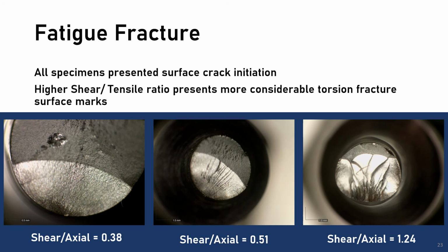With access to the fatigue fracture surface, we can now compare the fatigue fractures between different shear and axial ratios. We can see that lower shear in relation to the axial presents a fracture surface very similar to tension-compression fatigue tested specimens, whereas as we increase the shear in relation to the axial, we start to observe torsion fatigue marks, as we see, for example, for 0.5, and when we increase to a higher amplitude shear in relation to the axial, you can clearly see this high shear damage applied to the specimen.